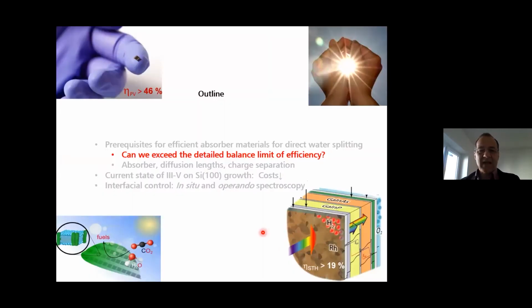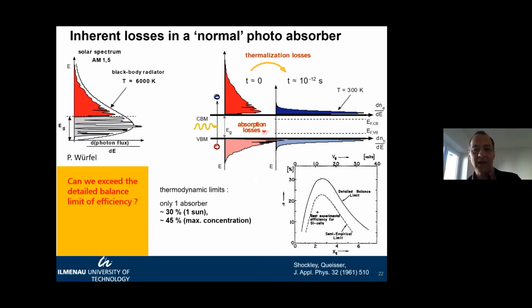Okay, there is one point which is always discussed, and this is the point: can we exceed the Shockley-Queisser limit? Can we exceed the detailed balance limit of efficiency? I just want to very briefly comment on this. What does it mean? In a normal solar cell, in a normal photoabsorber, we have severe losses, huge losses. One loss, of course, is that we cannot absorb light which has lower energies than the bandgap. And this is a huge loss. Another huge loss is that all photons which have higher energies than the bandgap of a semiconductor are immediately, in less than a picosecond, losing their energy down to the energy of the bandgap.